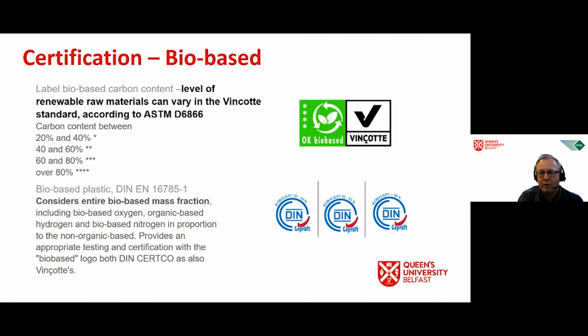So when it comes to certifying bio-based materials, there are some common standards, and two of them are the Vinçotte and the DIN standard. The Vinçotte standard is according to ASTM D6866, as you see, and this can be bio-based if it has a carbon content. So even if it has a carbon content of only 20%, it still can be classed as bio-based. However, the label does not show the actual percentage, but it shows the number of stars, where 4 stars can mean greater than 80%, and then fewer stars, 60 to 80, 40 to 60.